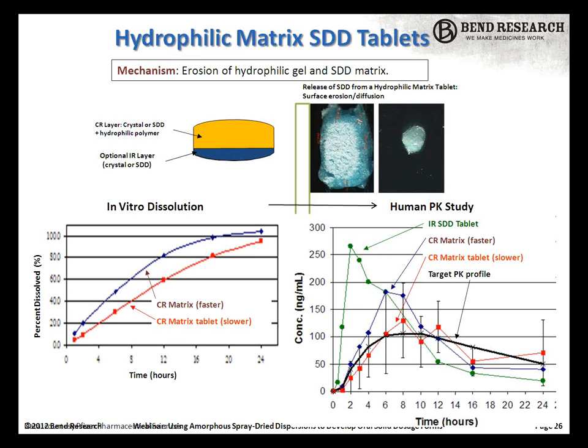What we tend to see is they tend to be a little bit more robust gels than just the regular matrix because of this interaction. And again, we can modulate with different molecular weights and loadings. The in vitro and in vivo correlation is shown on the bottom left here. That's a human study with an IR and two different CR dosage forms using the matrix technology.